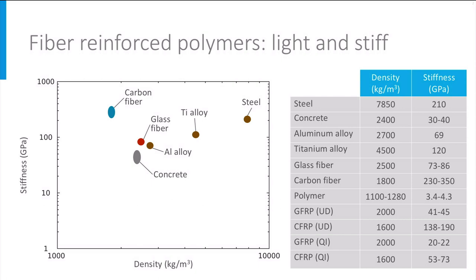The properties of glass are also good. However, these values are for the fibers only. Fibers have to be combined with a matrix material to form a material that can be used for structural applications. In FRPs, the fibers are combined with a polymer matrix. The polymers that are used — epoxy, polyester, maybe a thermoplastic like PEEK — are all very light with a density between 1100 and 1280 kg per cubic meter. But their stiffness is also much lower than any of the other materials in our chart. For FRPs to have a good stiffness, we must have a high fiber content. The composite stiffness is obviously going to be lower than the stiffness of the fibers. The good news is that the weight will also be lower, especially for GFRP with the heavier glass fibers.